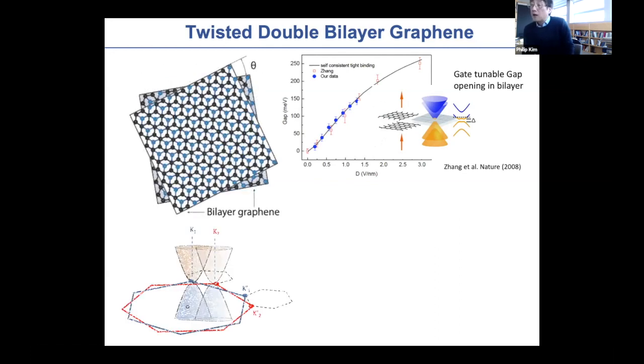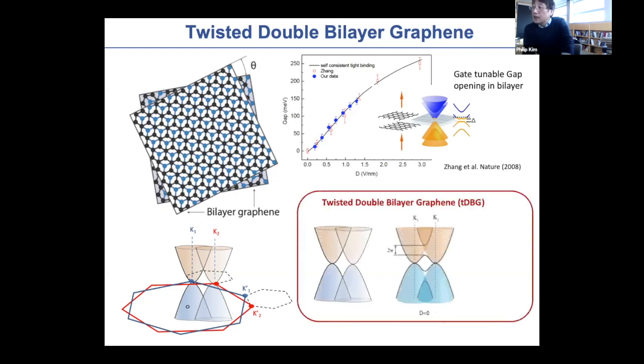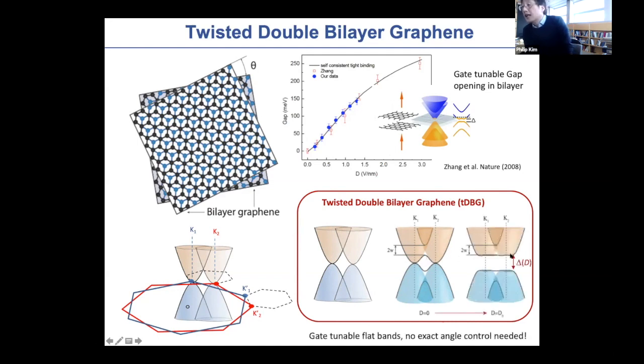So the idea is that once you stack these two Bernal stacked bilayers and make the twisting, there's a possibility that you can create this hybrid gap, and then by applying the electric field, you can probably open up the gap and control the size of the flat band by controlling the displacement field. So in some sense, in this particular case, you don't necessarily sharply tune the magic angle, but whatever angle is close to some small angle, you can use the displacement field to control this band structure such that you can control the flatness of this band.